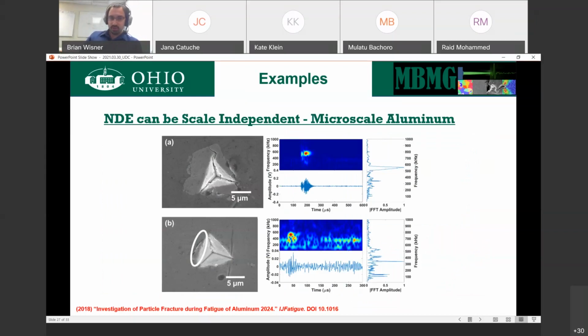Short answer is no. What I'm showing here is an example of indenting directly onto a particle to cause a fracture versus indenting on the aluminum. The reason I'm showing this is I monitored acoustic emission, energy release from these processes. When we fracture the particle, we get a very clear burst energy release. When we do the aluminum, we don't. That means if I want to reduce these fractured particles, acoustic emission on its own is a valid way to determine if my processing parameter changes have achieved my desired result. If I get fewer of these hits of these signals, then I'm fracturing fewer particles. Makes life really easy.